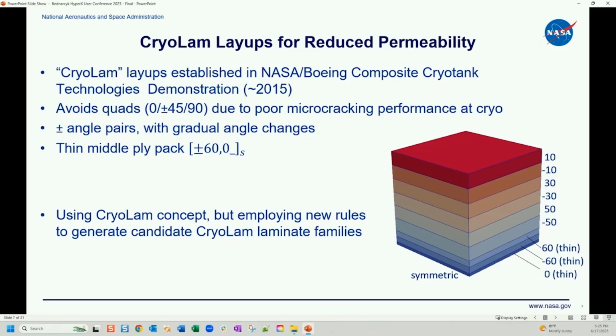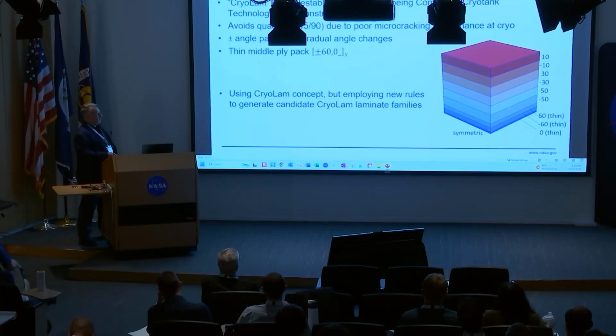If you look at the literature over the past 15 years on these types of structures and materials, that's pretty well known. So what they did was they used angle pairs, starting from a low angle and then going up, as you can see here, just an example. And then in the middle of the laminate, they put a pack of thin plies, and that pack of thin plies was always 60, minus 60, and 0. And this is symmetric, so you can see the thinner plies there.